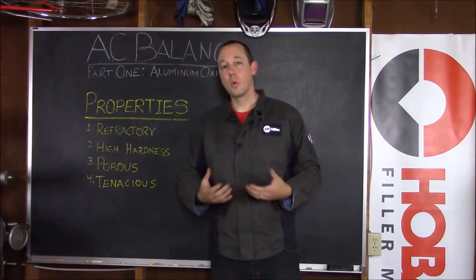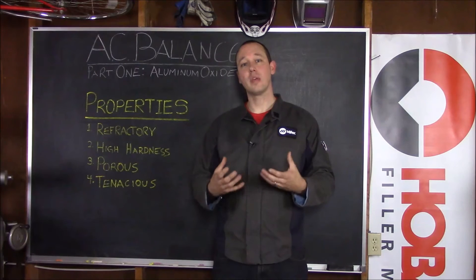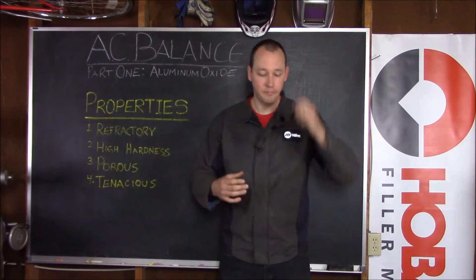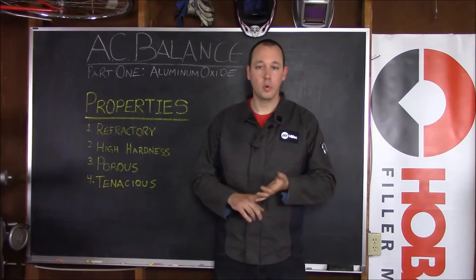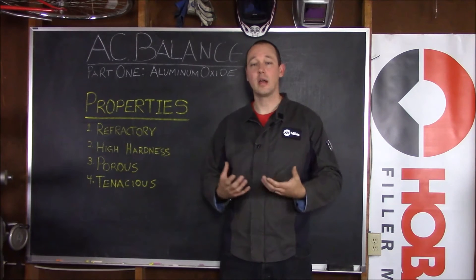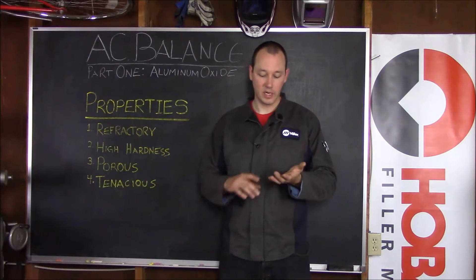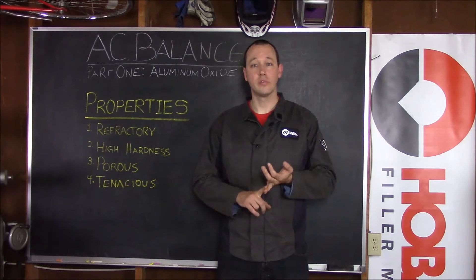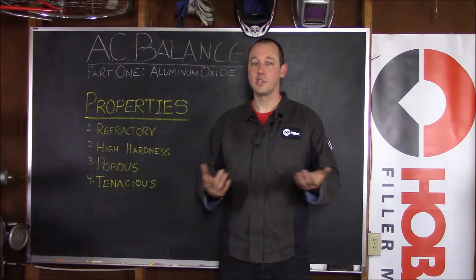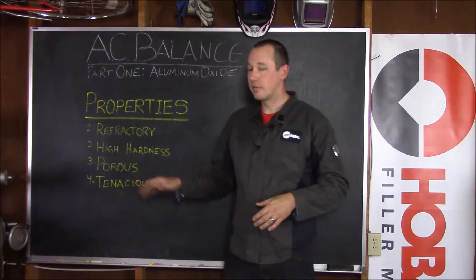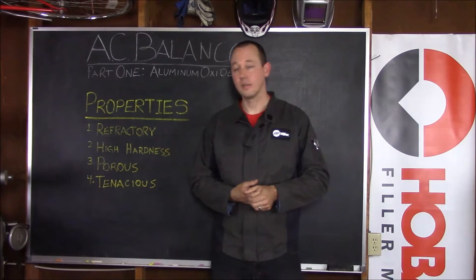Number three, it's very porous. It has a lot of pores and cavities inside of it, which in and of itself is not really a problem, but those cavities allow it to retain contaminants that we don't want anywhere near our weld pool. The number one cause of porosity in aluminum is hydrogen — it has a very high affinity for hydrogen. So anything with hydrogen in it we want to keep well away from our weld area: hydrocarbons, oils and greases are very bad, but something people don't frequently think about is water. H2O has got a lot of hydrogen in it, so the porosity inherent to aluminum oxide makes it a problem because it'll hold on to that stuff.